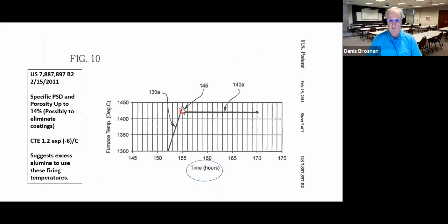Now, the fact that these guys have gone up with this little blip suggests to me they could have intentionally gone off the cordierite stoichiometry. They might have added a little extra alumina to this composition. They were trying to control the pore size distribution and attain a certain porosity. Well, one way to attain a certain pore size distribution is to allow alumina spinel to be formed in the production of cordierite. That's going to be a little bit of an expansion reaction, and also kind of serve as a framework in the body to kind of hold things together. So whether they were doing that or not, I don't know, but you can see there has been evolution in this technology. This was another Corning patent.